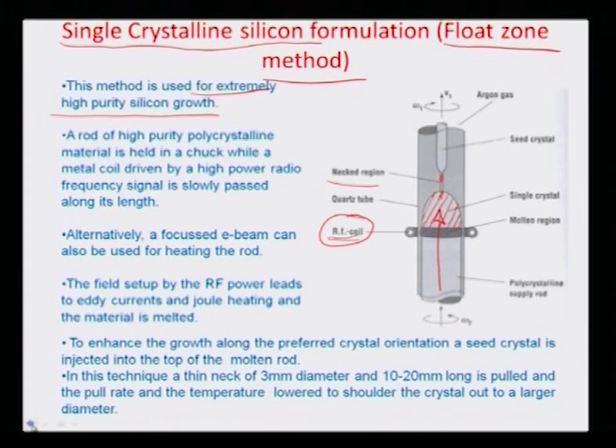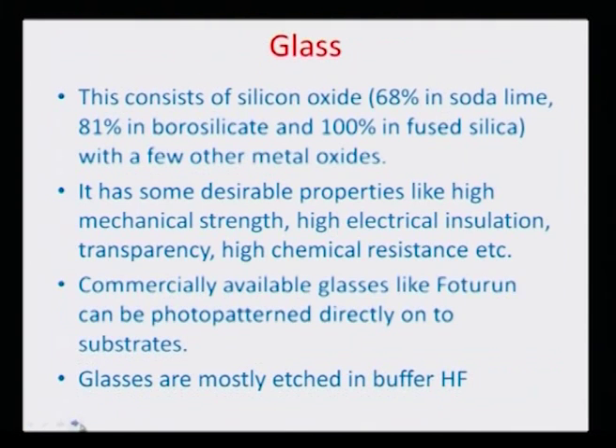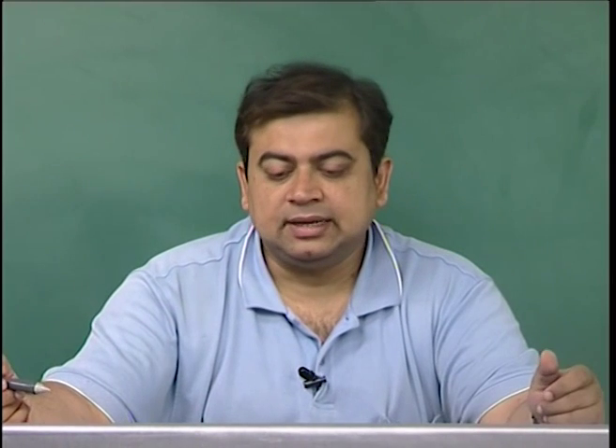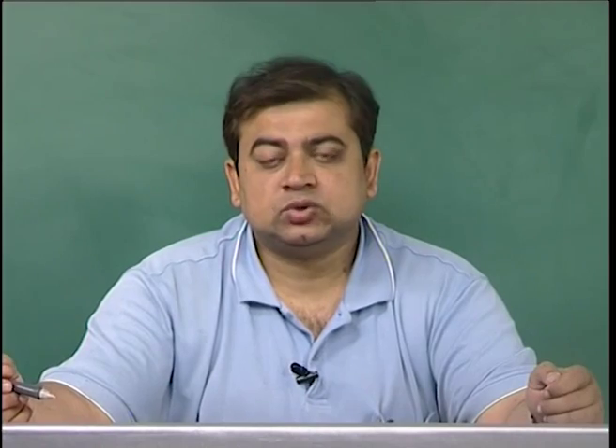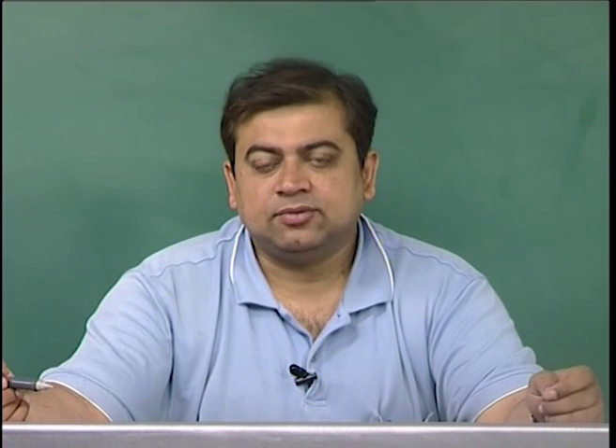So the other material of importance for microsystems fabrication, as has been indicated, is glass. Glass is actually chemically silicon oxide, and the content of silicon oxide, however, varies across different glasses. For example, soda lime glass would contain about 68% silicon oxide. Borosilicate, another variety of glass, would contain about 81%. And the highest and purest form of glass is quartz, really. It's fused silica, which is actually 100% silicon oxide.